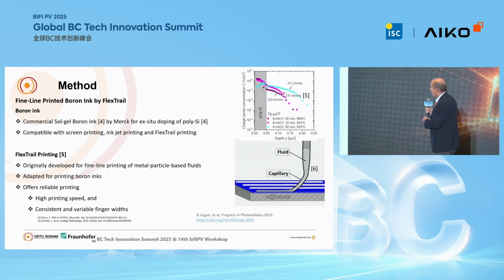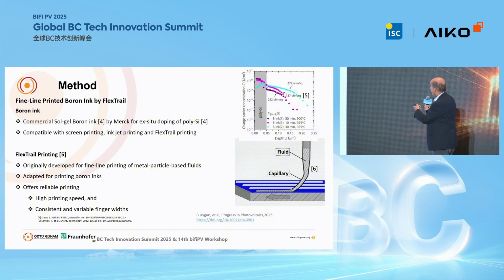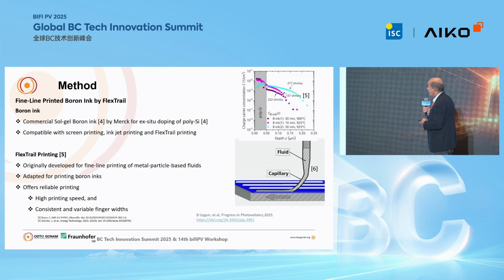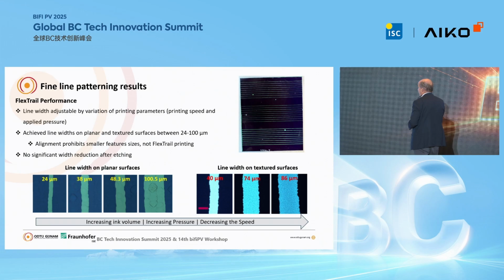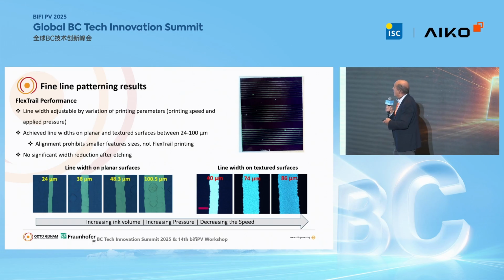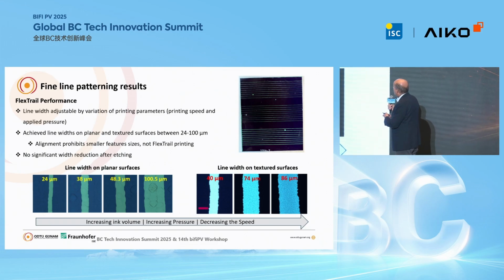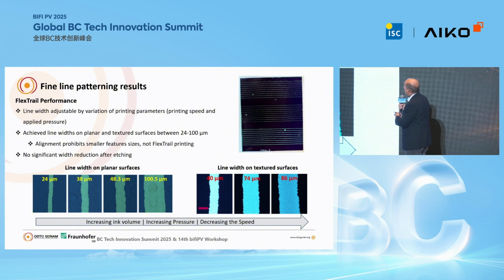And boron ink is applied by flex trail. And it's useful for doping. You can see the doping profiles obtained by using boron ink. So it can be very high speed and also very consistent with finger width. So the results are shown here. So we have obtained very nice polyfingers with the width changing from 24 micrometers up to 100 micrometers.